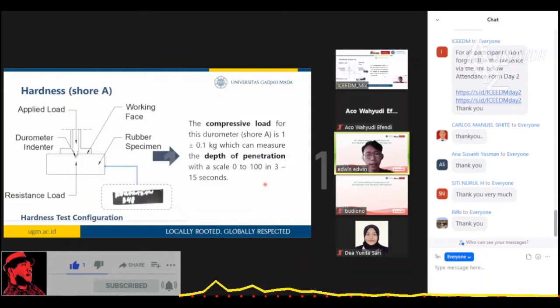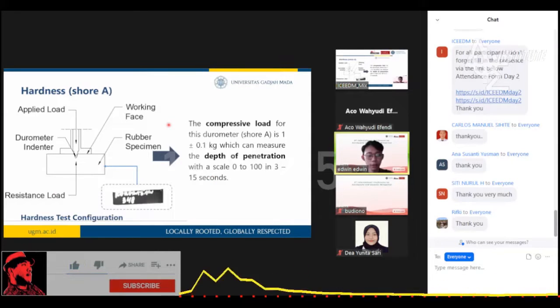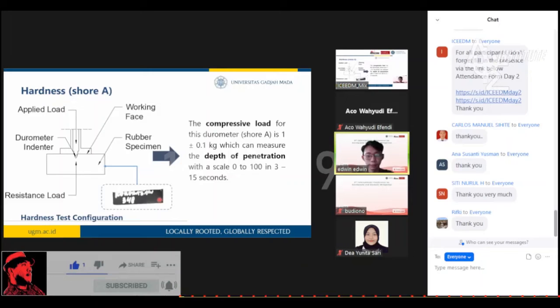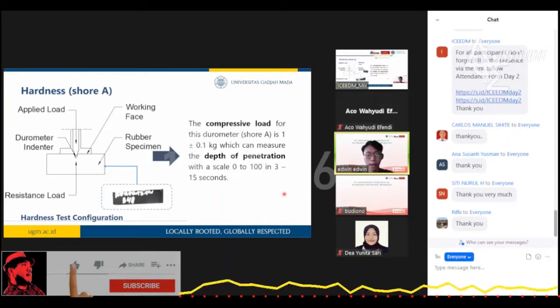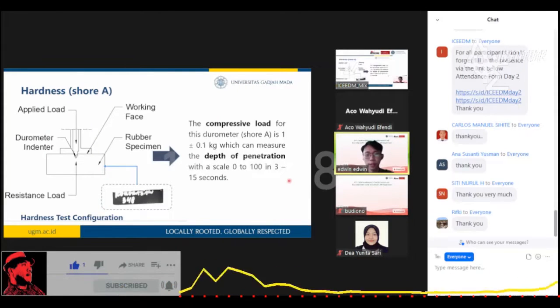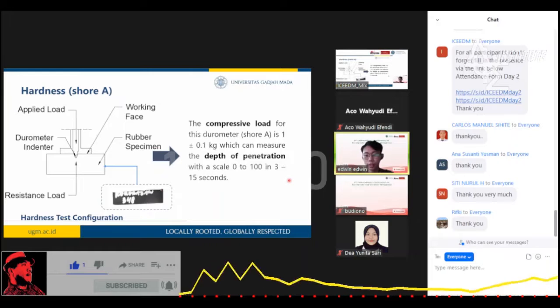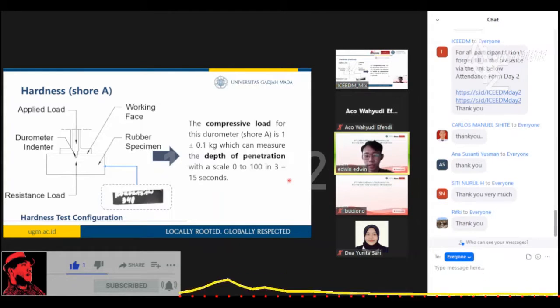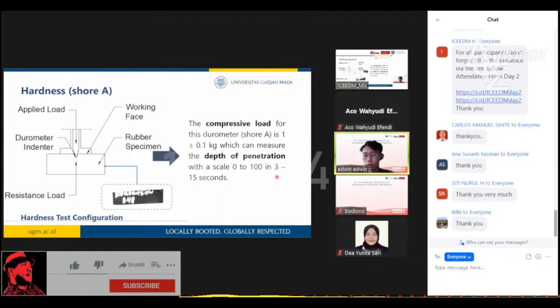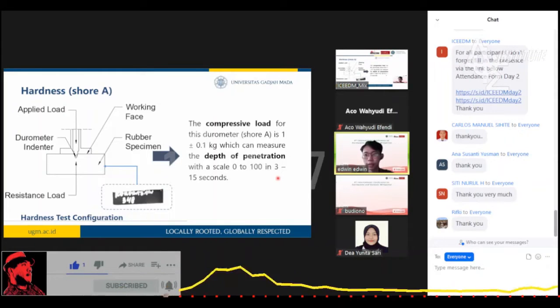After the tensile test, there is also hardness test, and this is the hardness test configuration, and this is the specimen used for the testing. For this test, compressive load used for this durometer shore A type is 1 ± 0.1 kilogram, which can measure the depth of penetration with a scale of 0 to 100 in 3 until 15 seconds.